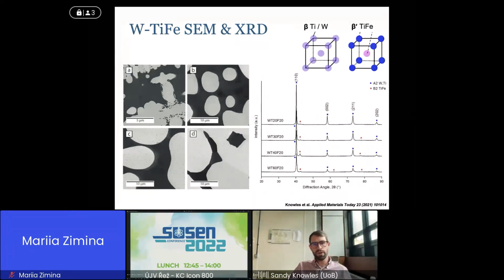So in this kind of study, one of the things we were doing was making real alloys. So we have alloys which are going from tungsten rich with 20% atomic titanium and iron. So these go across in increasing tungsten concentration. And what we see is we get different phases depending on the composition of the alloy and different volume fraction phases. But predominantly we get the two things we were initially interested in, which was this